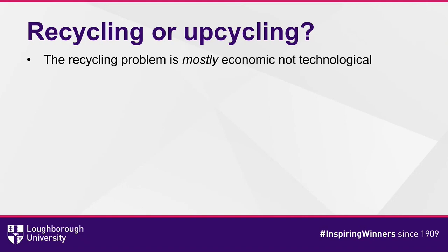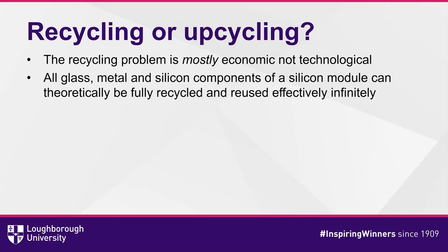That said, the recycling problem, if you want to see it in those terms, is primarily economic. It's not really a technological issue so much these days. Most of the materials, we've actually worked out ways of extracting them from a module. It's just not always economic to do it, which in itself is a problem. But we can get all of the glass, the metals, silicon components, and so on from a module. In theory, we can fully recycle them, and they can therefore effectively be infinitely reused. You can get into this cradle to cradle idea, and you can reuse that.